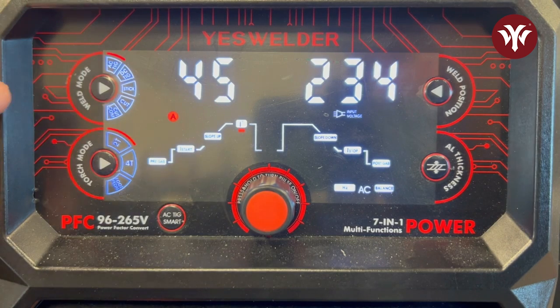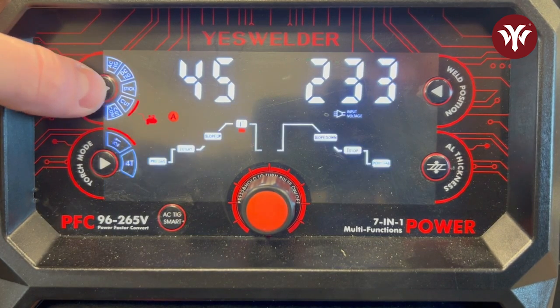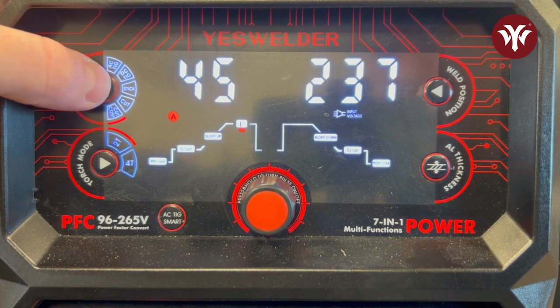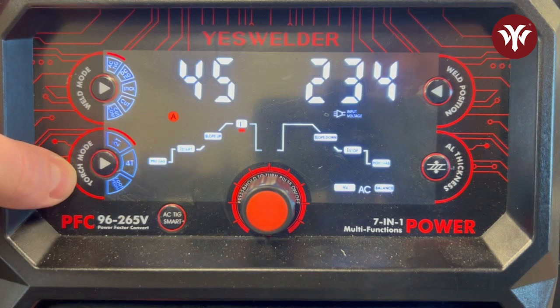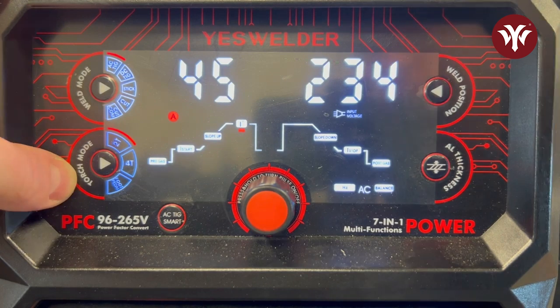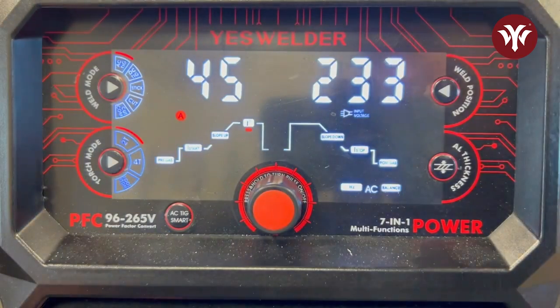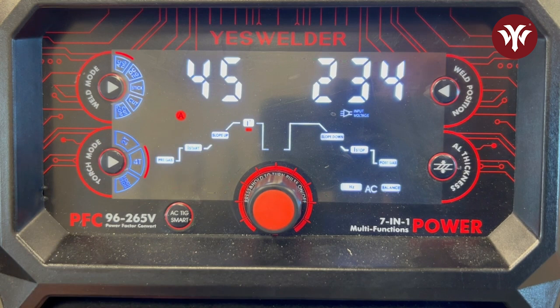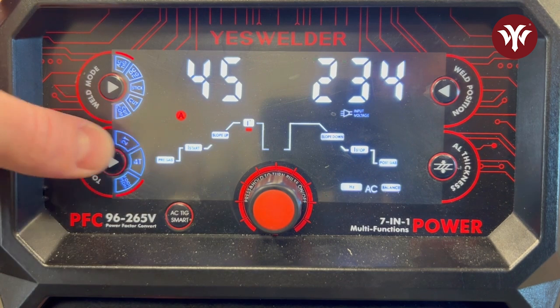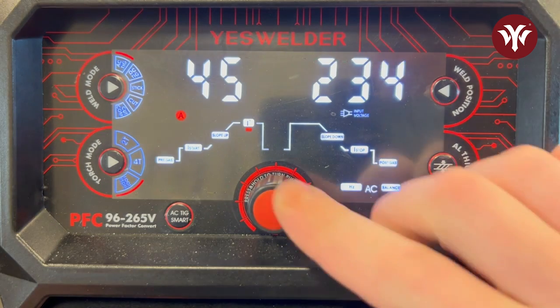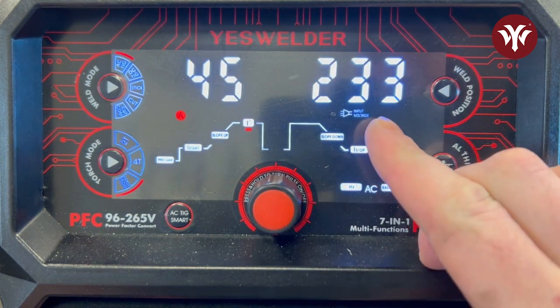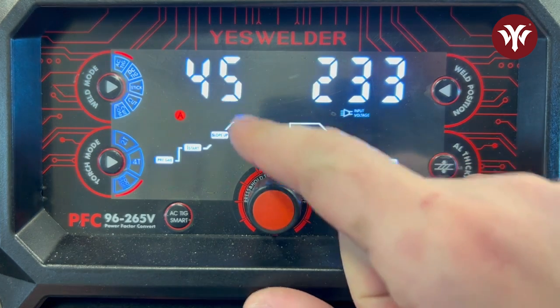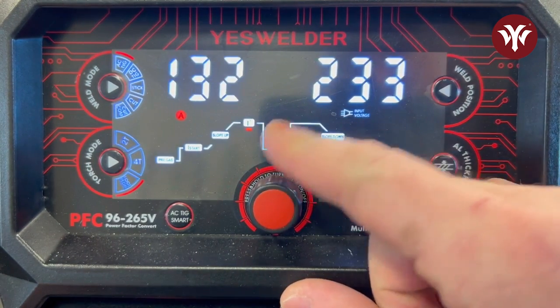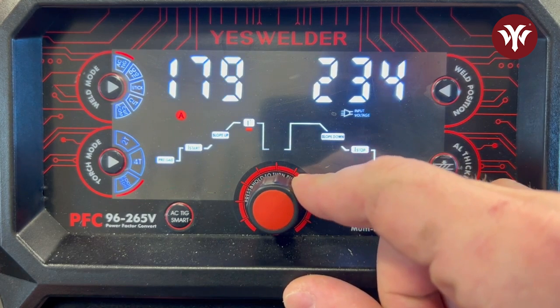This welder here, you select the weld mode: AC TIG, DC TIG, stick, cut, cut com, and then here are your torch modes. So 2T is your button on your torch, because this one has a torch button. 2T is momentary, so the arc is only established while the button is being held. 4T is push on and then push off, and then foot pedal, well, I think that's pretty explanatory. Then some of the other settings you can go through. As you can see here, input line voltage is 233 volts. The machine right now is set at 45 amps, which we're going to be using significantly higher than that. I'll be setting to about 180.